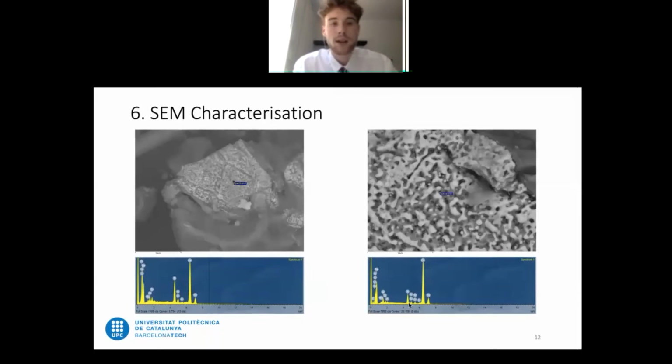Effectively, as we've already established, we can't really gauge a good enough approximation of what is occurring on the left side of this image. However, by viewing the elemental compositions, just by seeing these two images, we can see that the amount of titanium in the image on the right is far less than that on the left, which is to be expected, seeing that it has been reduced for double the time.